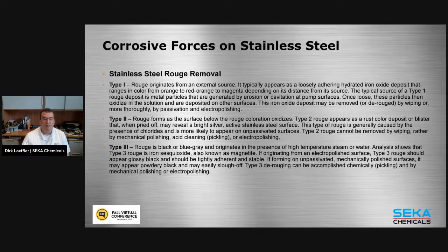Type 3, again, this is probably the most difficult to remove. This one is, I must say, very hard to remove with chemicals. Extensive pickling might work, but you're literally taking quite a bit of the layer of your stainless steel. But it can be removed by either mechanical polishing or electropolishing. So that's definitely something possible. But generally you're looking at a very expensive way of refurbishing your tank, and definitely usually outside help.